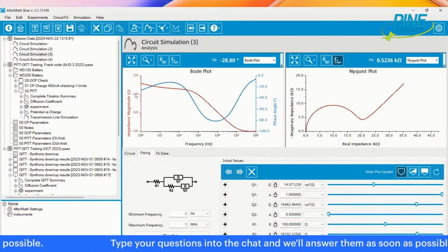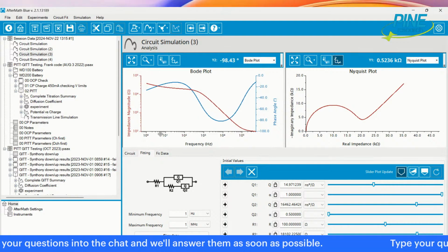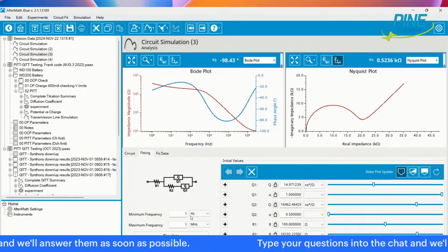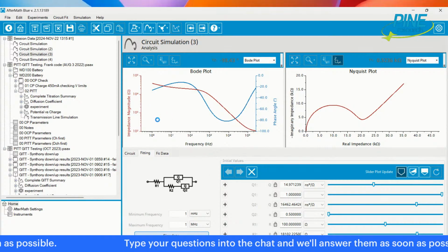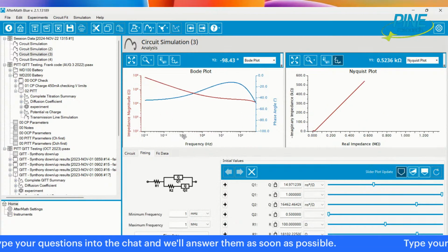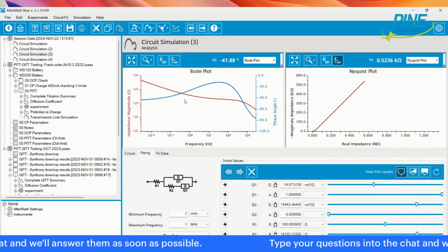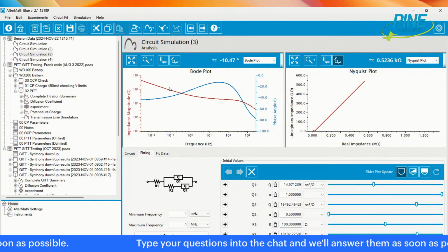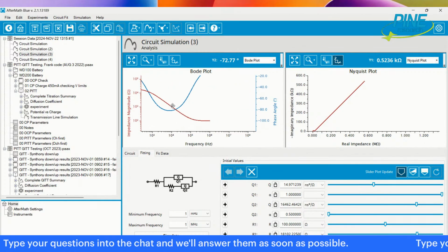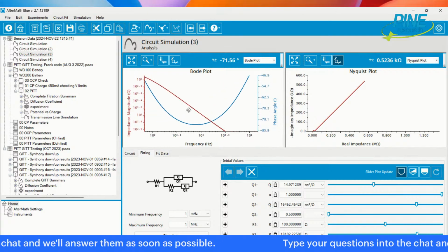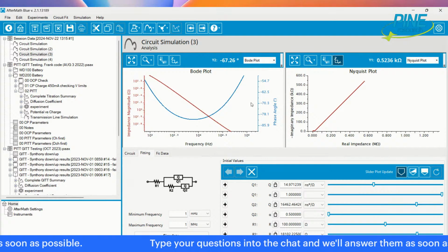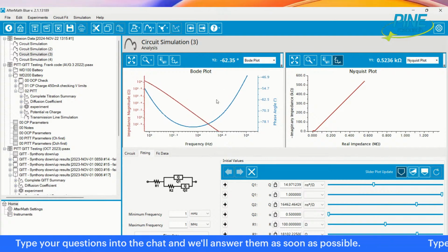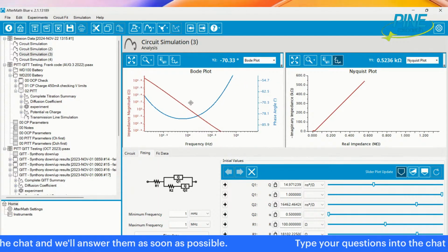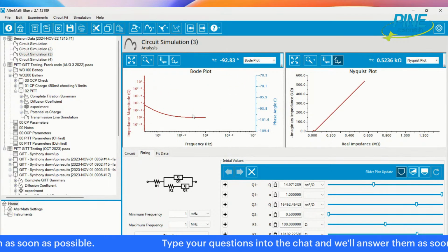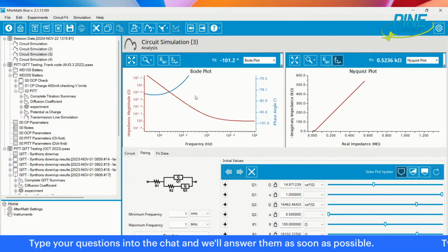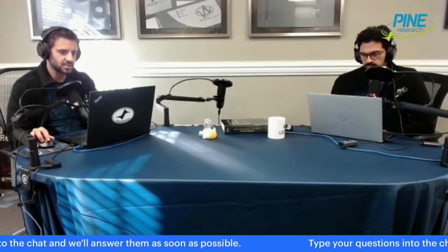The phase angle will generally start decreasing towards 45 degrees as I go lower and lower in frequency. So there you go, now it's minus 45 degrees. And the impedance magnitude also continues to go up at a slope, but it's a different slope. This slope right here is the one that correlates to mostly capacitive behavior. So you're looking for peaks in the phase angle plot that correlate to semicircles. You're looking for straight lines that correlate to mostly capacitive behavior over that frequency range. Plateaus correlate to mostly resistive behavior over those frequency ranges. That's what I would say to you for Bode plot features.